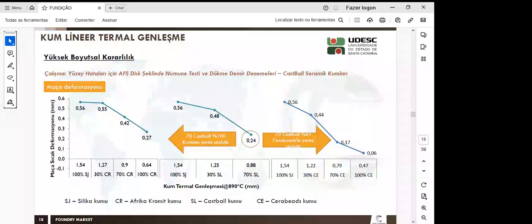This graph shows the correlation of deformation with thermal expansion. We have different mixes, different compositions: silica sand with chromite in the first graph, in the central graph silica sand mixed with Castball, and in the last graph silica sand mixed with Cerabeads. And the results are the deformation of the casting in millimeters.